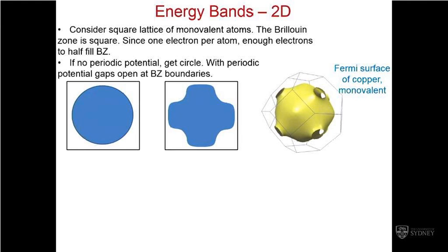And for example, this shows the Fermi surface for copper. So you can see it's very much kind of spherical, but it has these kind of necks that reflect that it is not a perfectly free electron-like kind of material. And a lot of experimentalists spend a lot of energy and time mapping out the Fermi surface of complicated materials, usually using angle-resolved photoemission.